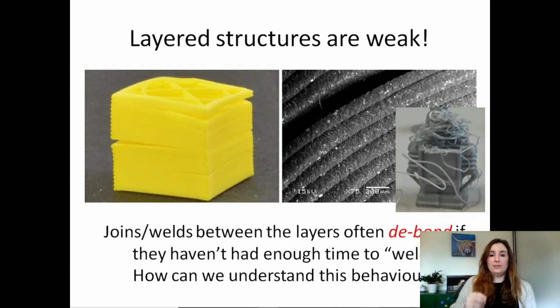As you've seen, 3D printing is a layer by layer technique. So we make these layered structures where there's lots of joins or weld lines between those deposited filaments. It turns out these weld lines are notoriously weak, so they debond or come apart very easily if they haven't had enough time to weld together, or equivalently if you haven't got your print settings quite right. And this is exactly what's happened to my robot here. The welds have just sprung apart and made this mess.